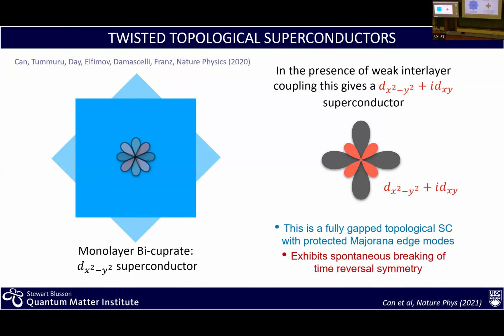And here is what the change is. Instead of dx squared minus y squared, you go to a system, and you can show that theoretically in various ways, which now has an additional component, i dxy. What it means in practice is before you had a superconductor with nodes along the diagonal, but now because there is interaction, the pairing is non-zero everywhere. Okay, that's just a quantitative statement like that, but in fact, is not.